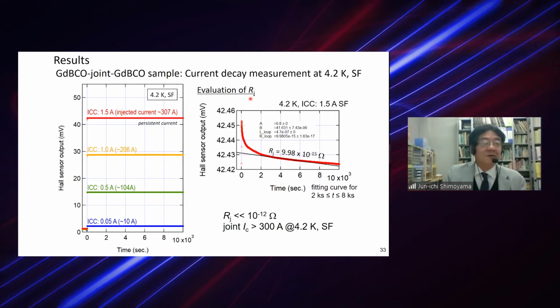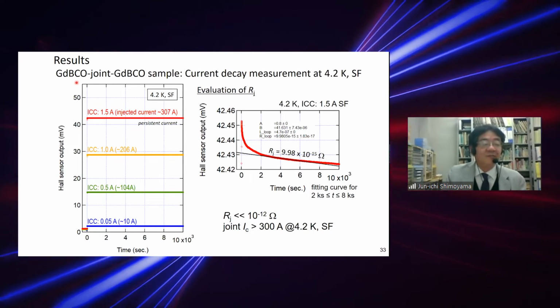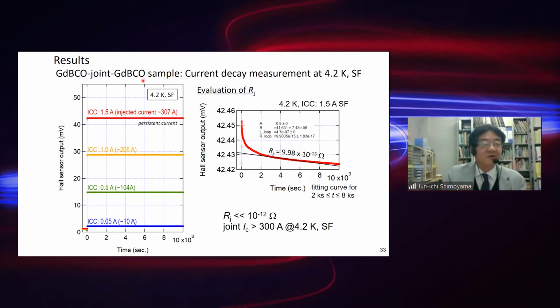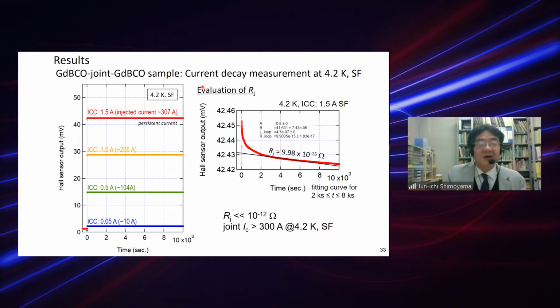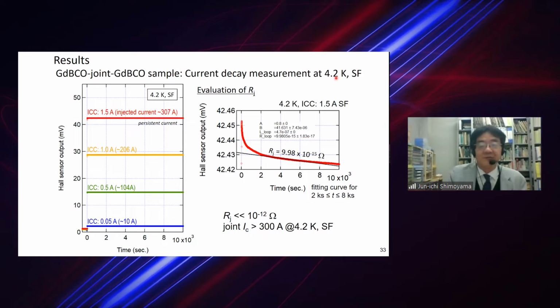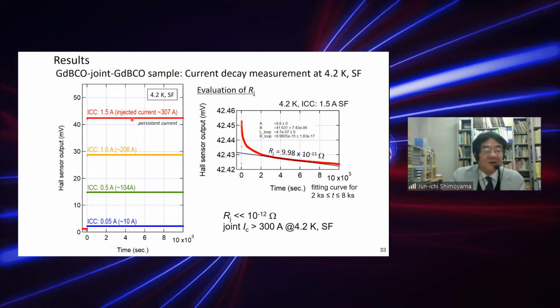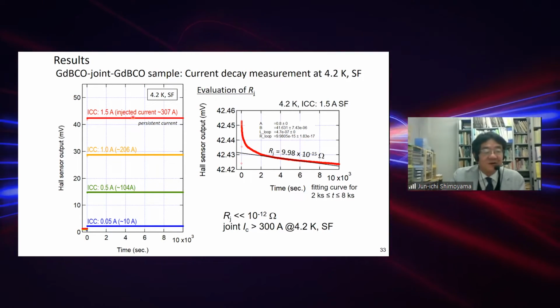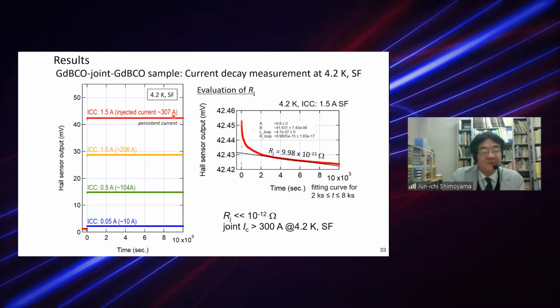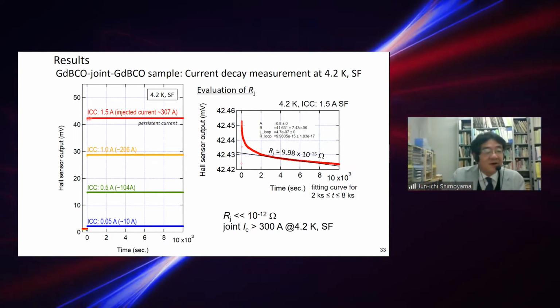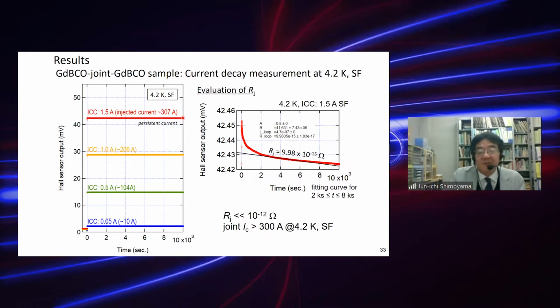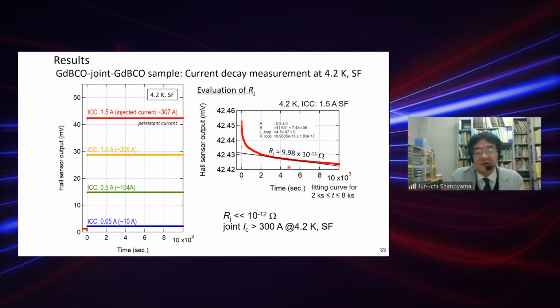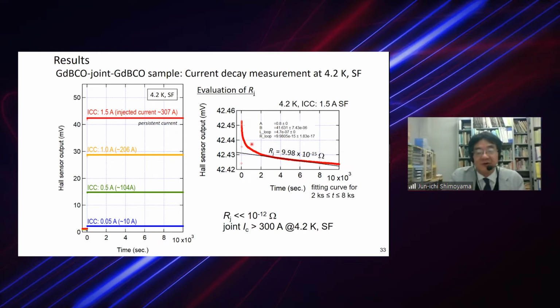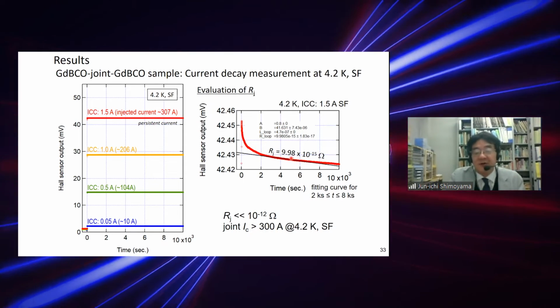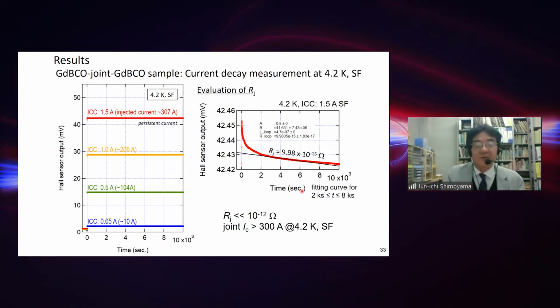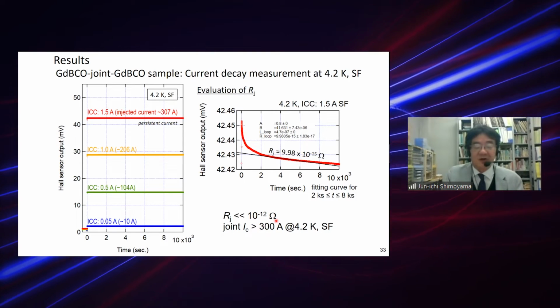So for the gadolinium conductors joined by the intermediate layer, current decay is very, very small at 4.2 Kelvin, as you see here. Even under the injecting current over 300 amps, current decay with time is very, very small. And in this case, we can calculate the joint resistance to be almost 10 to minus 14 ohms. This is much lower than the required values.